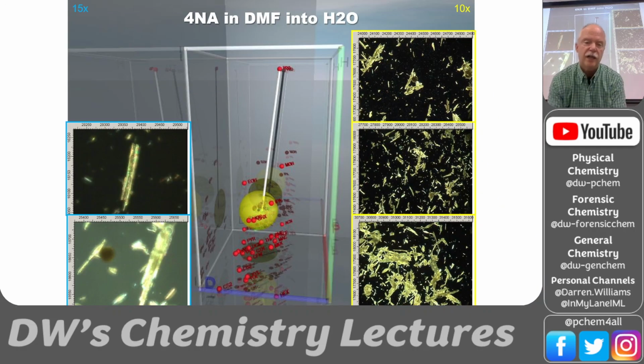So this is what it looks like in the Hansen solubility parameter space, okay? So this is going straight into water. So here's the nitroaniline in DMSO, dimethyl sulfoxide, and DMF, dimethylformamide, and it's going straight to water, and it's exiting its solubility sphere right here. So once you put 1 mil of this solution into water, as soon as the solvent sphere changes and gets outside this solubility sphere, you start to form precipitates.